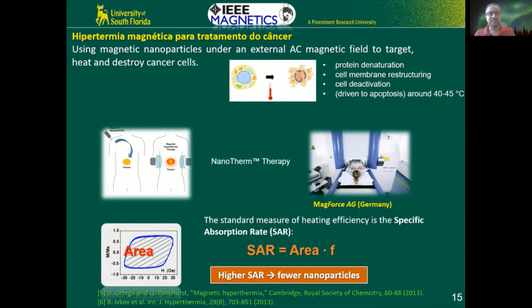I mean, think of it this way. Each of these magnetic particles is a large superparamagnet. They're almost like a single small ferromagnet by themselves. And when you apply a high frequency AC field, the magnetic moment tries to follow the high frequency, but they cannot, they go out of phase. And because of that, you can generate these kind of hysteresis loops.